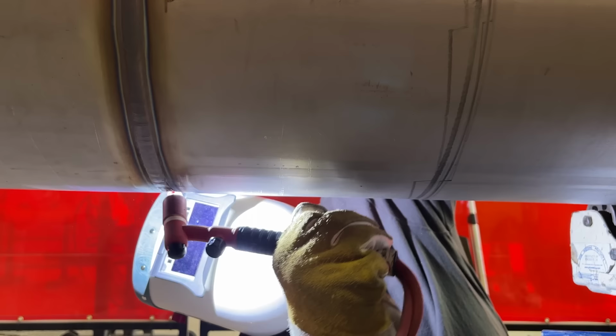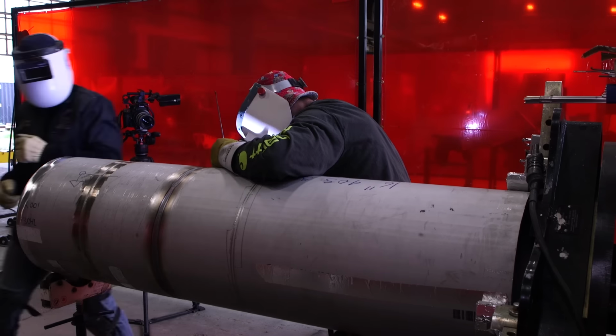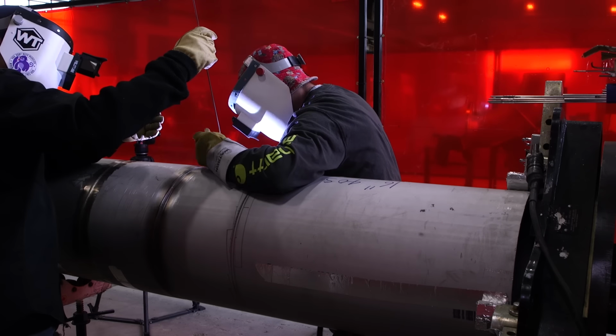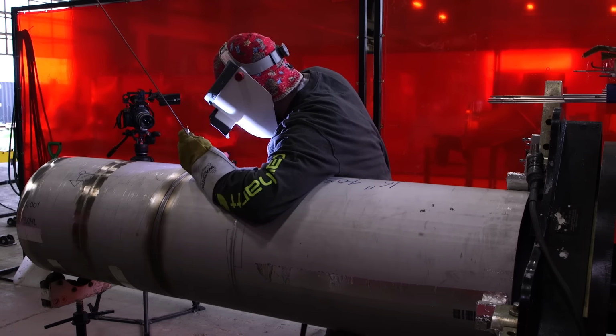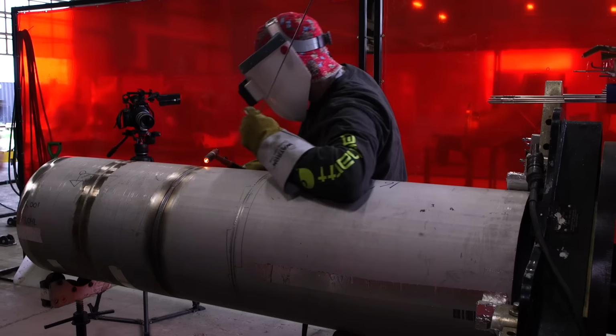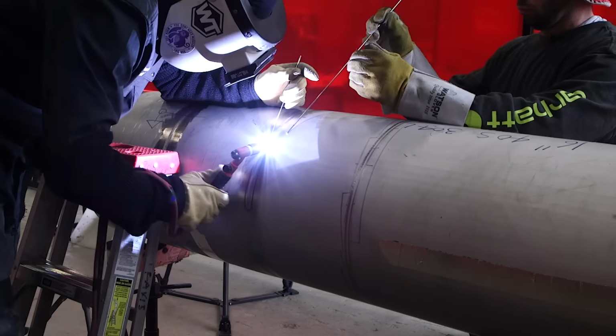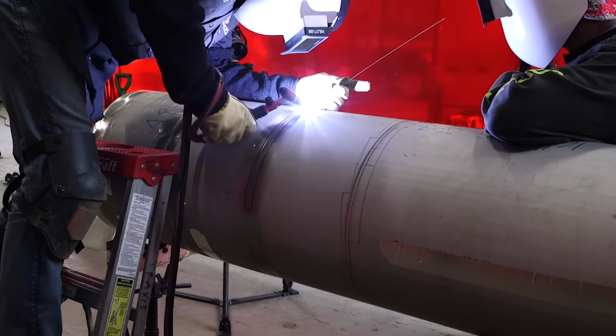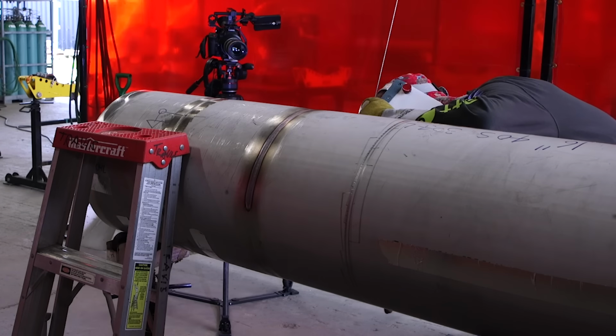Originally at the bottom I started with the TIG torch away from me. It's just a little bit easier, it's a little bit longer to reach. It's easy just passing another wire here, so we'll go further up the pipe. If you're able to see it, left bevel and right bevel, when I move to the right bevel, my left bevel, the puddle solidifies pretty quick there. And I'm able to stack my liquid weld puddle onto that previously deposited metal, which has solidified. That's how I'm able to get deposition over a distance.